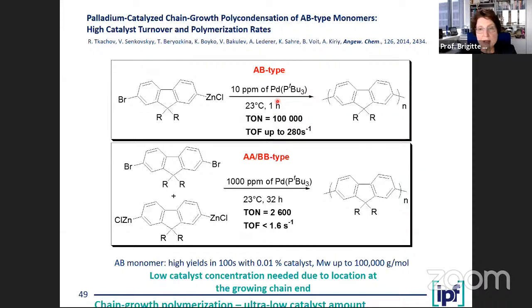And we can also reduce significantly the catalyst amount. I mean, that's one problem. The catalyst in conjugated polymers should be as low as possible because it changes the properties of the material significantly, the electronic properties. So when we have such palladium catalyst chain growth polycondensation, we can get a product at room temperature in 1 hour with 10 ppm palladium. And if we use a conventional method of an AABB type monomer, we need 100 times more catalyst, and we need 30 times more time to get a similar product out of it. And our molecular weights are even much better than what we got from the other one.